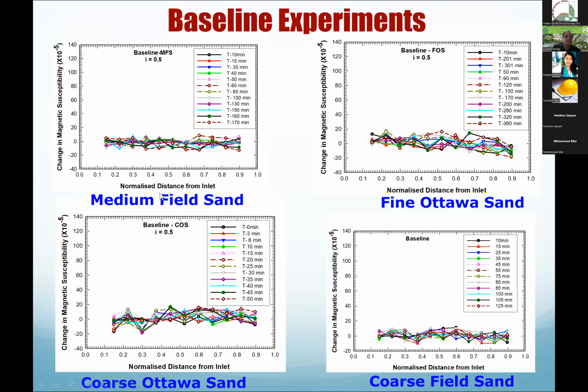So what I'm trying to show you is, after a certain time, we take out the samples, or during the experiments, remember that magnetic susceptibility meter I showed you. At different times t, we are measuring with the magnetic susceptibility meter what the change in the magnetic susceptibility is, right? You see there's not much change here using the bare nanoiron, right? So here also there's not much change. Here also not much change. Here also, with 4 different sands, using bare nanoiron is not making much difference.